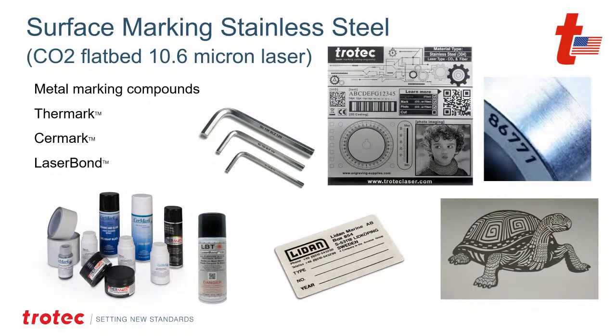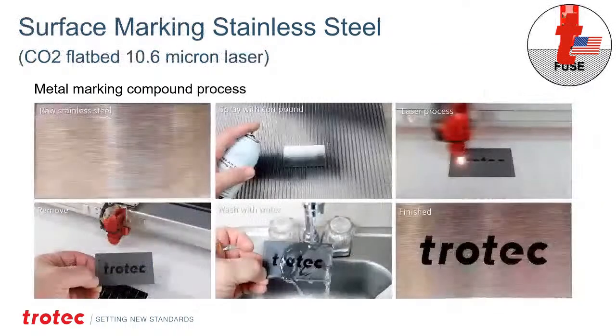The way the Thermark and LaserBond works is this. You basically take raw stainless steel, and I have to indicate raw because the metal cannot have any type of clear coating on it. Clear coating meaning some type of clear paint, polyurethane, lacquer, varnish, or anything like that. It's got to be an actual raw metal. This process also works with any metal, as long as that metal is raw and there's no clear coating on it. So you take that raw metal, you spray it with the compound.